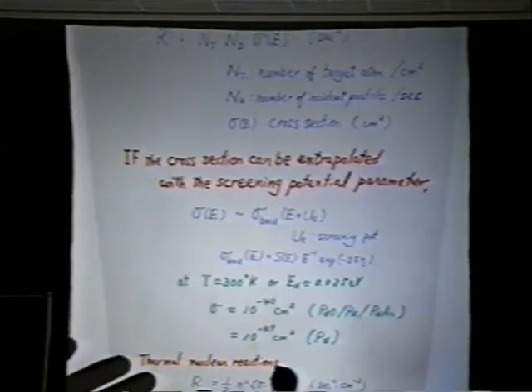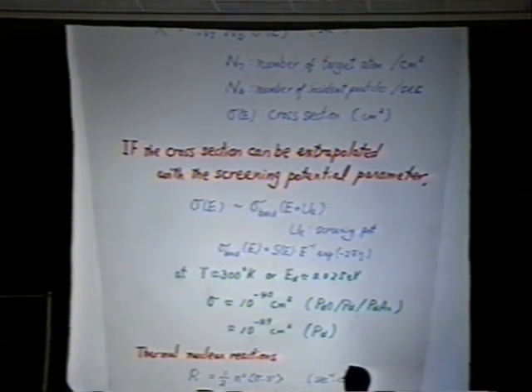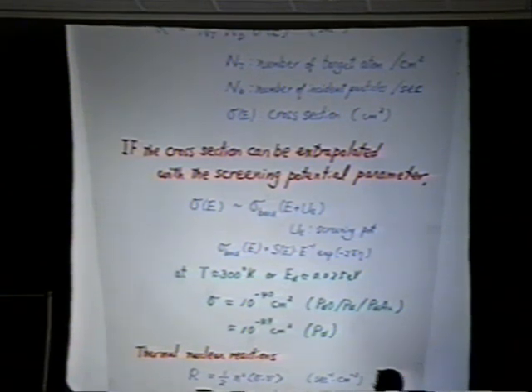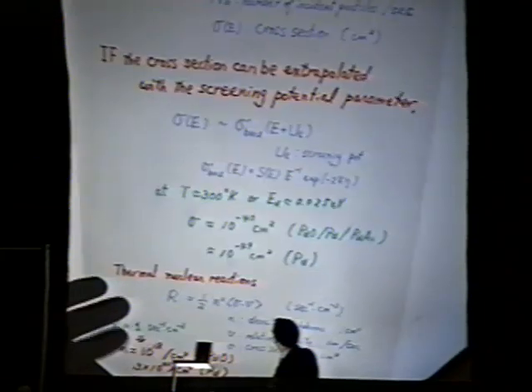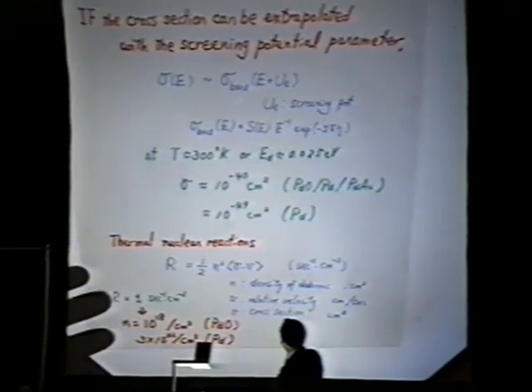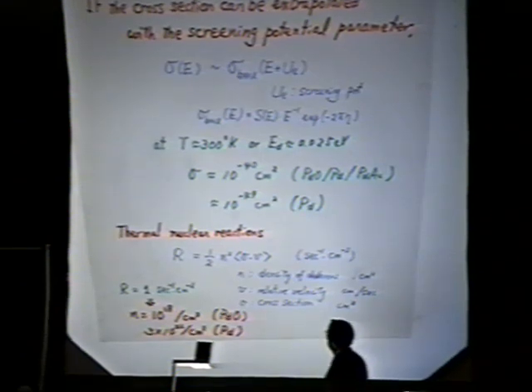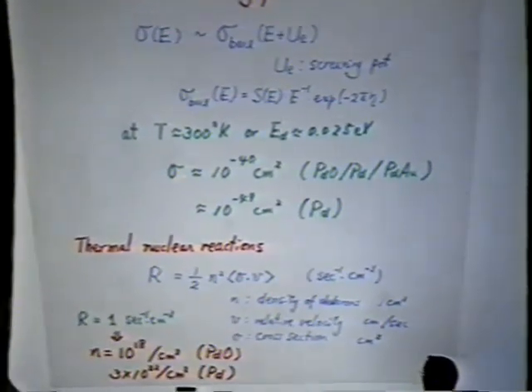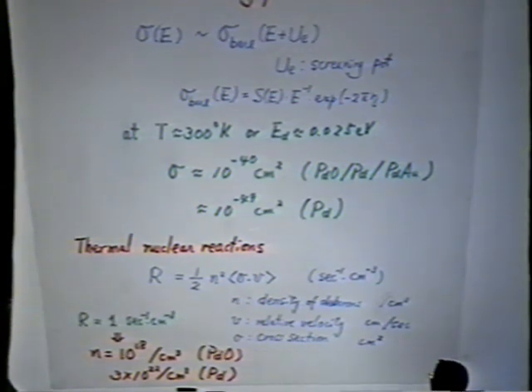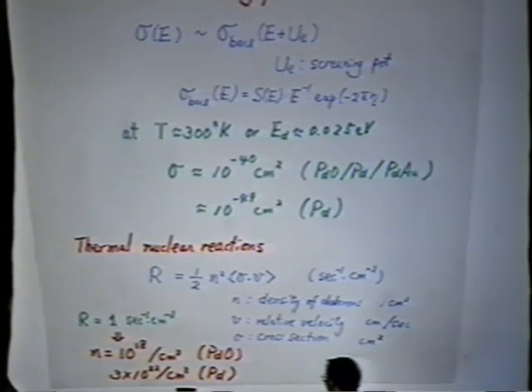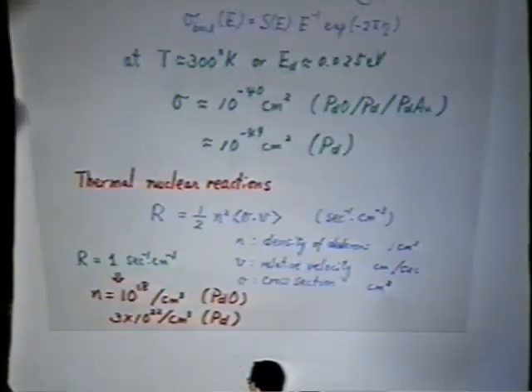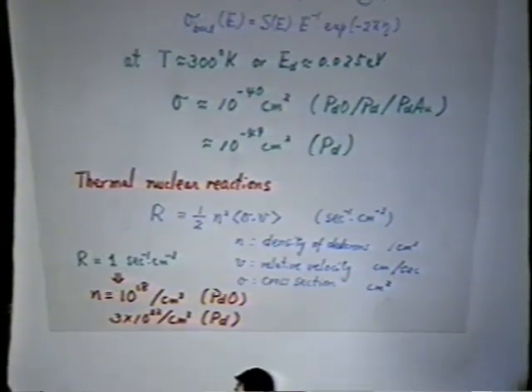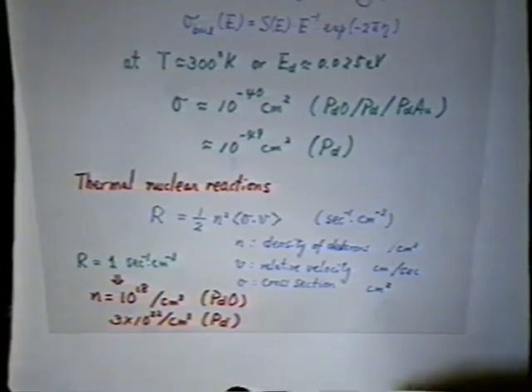If the cross section can be extrapolated with the screening potential parameter, as I showed you, 600 electron volts for PdO and 250 electron volts for Pd, then if we extrapolate it to room temperature, the estimated cross section is something around this range, 10 to the minus 49 to 10 to the minus 40 square centimeter. And that brings this rate. That's it. Thank you. Thank you very much.